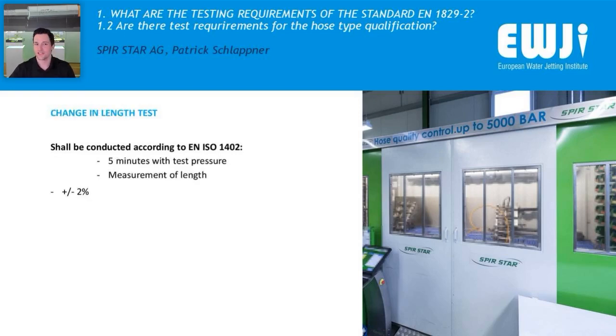The change in length test is also conducted according to EN ISO 1402. Here we test hoses for 5 minutes with the test pressure. Any change in length shall not exceed plus minus 2% of the original length.